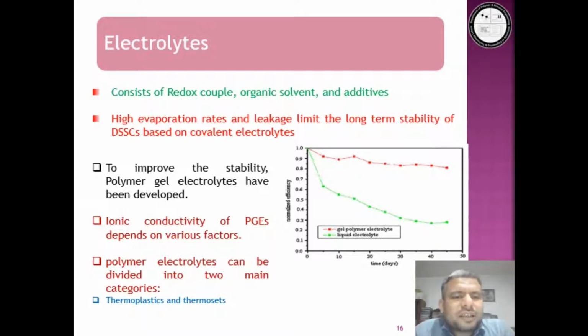Ionic conductivity of polymer electrolytes depends on various factors such as the molecular weight of the polymer. The higher the molecular weight, the lower the conductivity. Similarly, the concentration of polymer: concentration of polymer inversely affects the conductivity of the electrolyte. Similarly, the concentration of salt enhances the conductivity of the electrolyte.